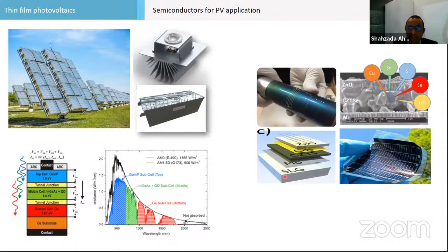And then this is a soda lime glass. Then you sputter molybdenum on top of it. And you have a formulation of copper, zinc, tin, and selenide. And by chemical bath deposition, you put cadmium sulfide, and then you sputter zinc oxide or ITO. This is not very efficient, but it's very attractive. The efficiency is 12.6% maximum, and 10-11% we also achieved in our laboratory. But this is also a solar cell which is more stable.